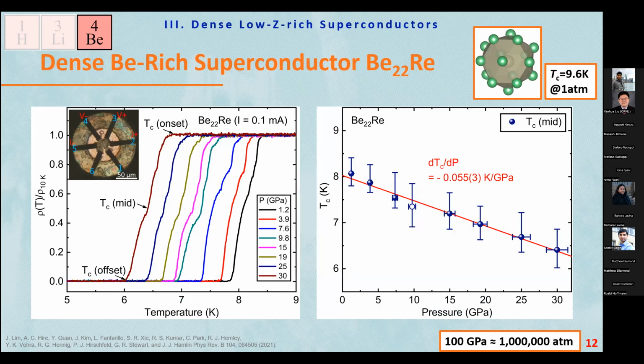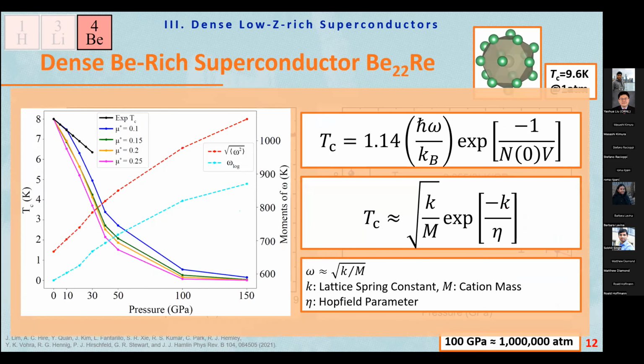So it's slowly going down. We went up to 30 GPa, and TC goes slowly down. And theoretical estimation suggests that TC will keep going down to 0 at 150 GPa. So with these beryllium compounds, so far, we didn't have much success increasing the TC like the hydride. In this case, we think that lattice stiffening plays a role. In the TC calculation, there's an exponential term with the lattice spring constant, and lattice stiffening under pressure plays a very important role in this compound, which decreases the TC with pressure.